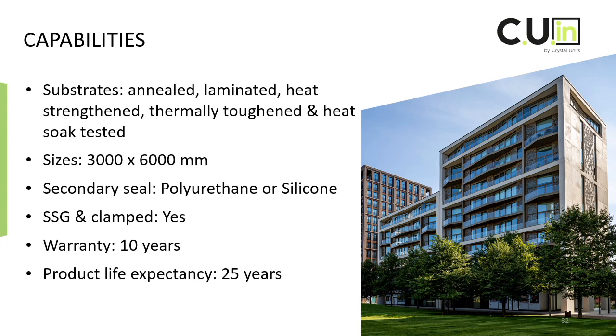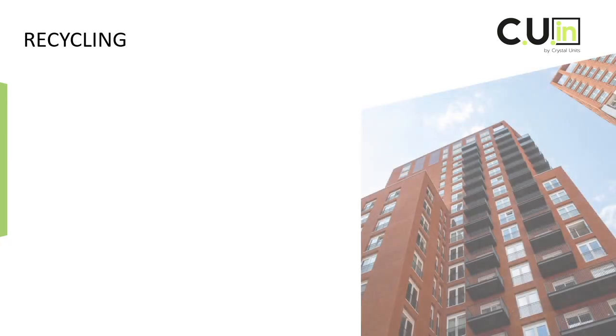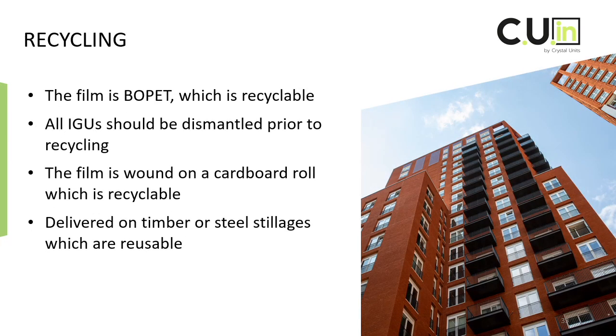Capabilities of IGUs with invisible suspended film technology include: the glass substrate can be annealed, laminated, heat strengthened, thermally toughened, and heat soak tested. The maximum size is 3000 mm by 6000 mm. They can also have a polyurethane or silicon secondary seal, providing structural integrity and functioning as a barrier to water, air and other substances. IGUs with suspended film are suitable for structural silicone glazing and can be clamped. They have a warranty of 10 years. But the product's average service lifespan is at least 25 years, as with standard IGUs. The film is made of a biaxially oriented polyethylene terephthalate, which is recyclable.